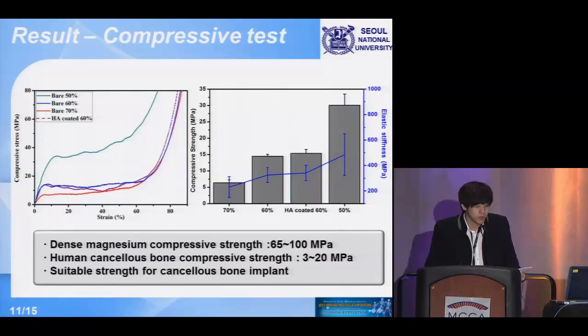And we checked the compressive strength and stiffness of the porous magnesium with different porosities. As porosity decreases, you can see that strength is increasing, as everyone would know. And as you can see from the data, the porous magnesium was not brittle but ductile, which we wanted. And after coating with hydroxyapatite, there was no significant change in the mechanical properties, and